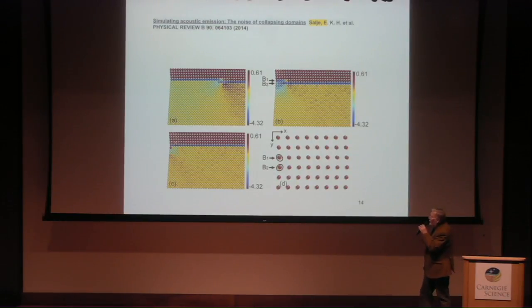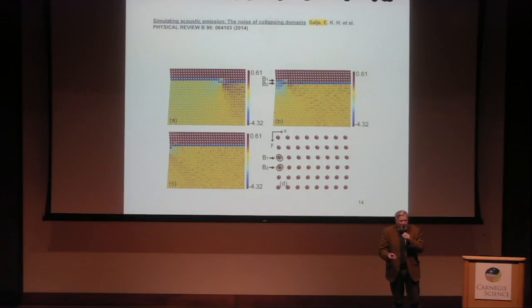The fastest one actually found, I mean, it's very similar to that, we found by computer simulation, by MD simulation. And so we looked into all sorts of domain boundaries, put external fields in, and saw how fast they could move. And the fastest we always found are these kinks. So you have a wall, you have a kink, and there's a wall again. And then here, of course, you have Eshelby and all that strain fields. Now, if you put the field in such a way that this thing moves to the left, it goes to the left, and when it hits the surface, it emits an acoustic signal. Right? Because you change these atoms.